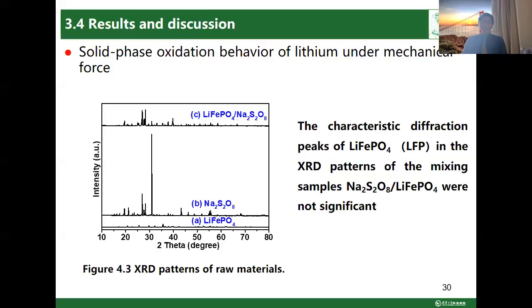Compared with the sodium salt, the characteristic diffraction peak of lithium salt in the XRD pattern of the mixing sample is not significant. This can be attributed to the masking effect of this reagent.